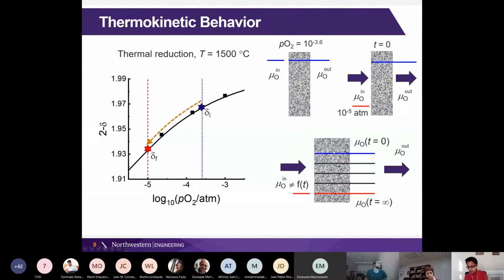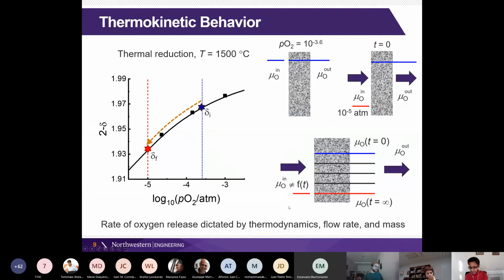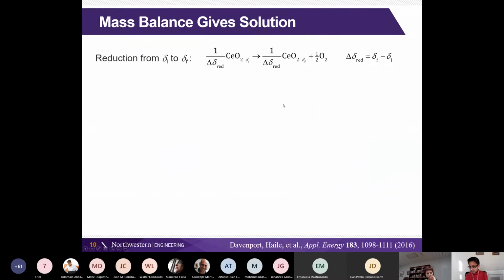That's why we use that open porosity material. And we want to track how the chemical potential, therefore the oxygen partial pressure emerging from here, changes with time. We know the gas flow rate and we know the mass. So these are the things that dictate the overall behavior: this thermodynamics, the gas flow rate, and the mass of the material. Okay, so now we're going to have just a little bit of equations here.